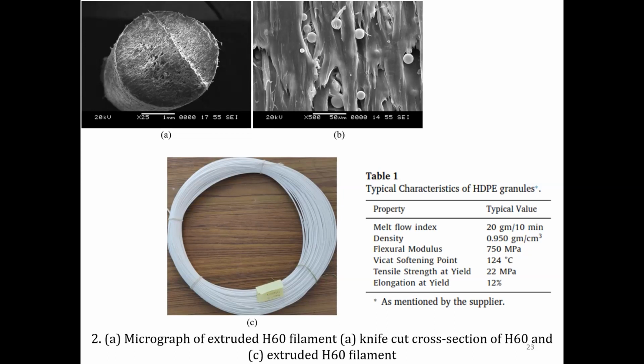So HDP pellets of H20 to H60, which were the outcome of the twin screw extruder, were dried at 80 degrees C in an oven for 24 hours, because we want to remove the moisture, if any is present, before gravity feeding into the hopper of a single screw extruder. Now, you know why we are using a single screw extruder. I did mention that in one of the earlier slides. This is to draw the filament of an appropriate size.